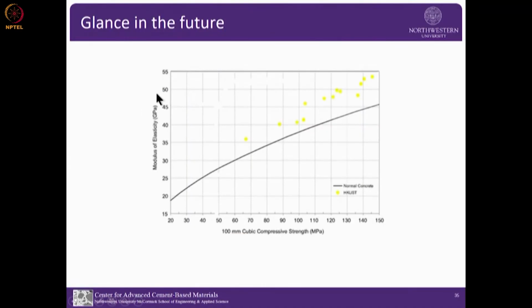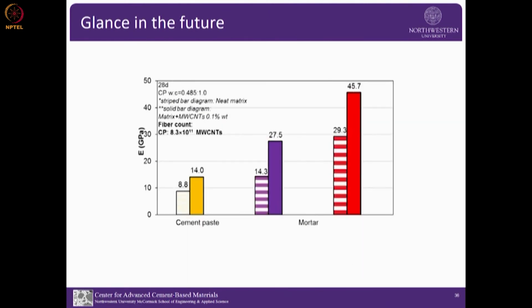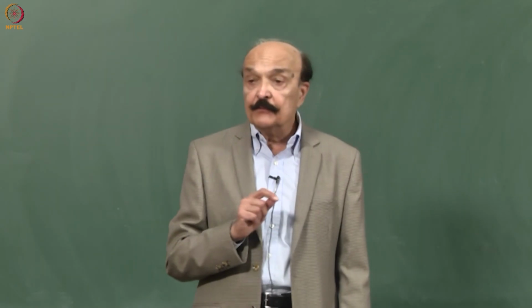Before I go there, currently this is, for example, from the code in Hong Kong, modulus versus compressive strength. If you want, let's say, 50 gigapascal modulus, we are talking about 150 compressive strength. So keep this curve in mind. People are trying to do better than this curve, but still you need high compressive strength to get that modulus. So we went and did this with cement paste, mortar, and concrete. Look at this: this is the modulus in gigapascal, for cement paste, unreinforced and with 0.1%. But look at it, with the same amount of carbon nanotube, the increase in mortar is even higher.